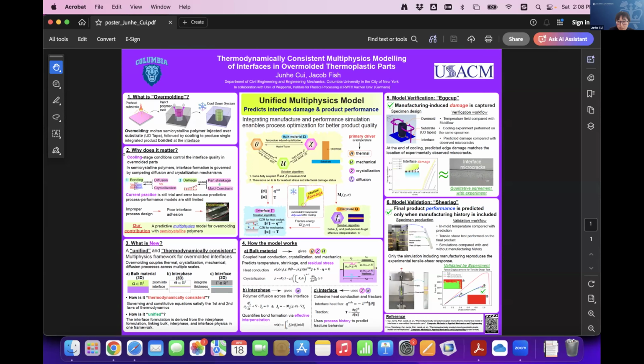Several physical mechanisms happen at the same time. Polymer diffusion across the interface helps the bonding. However, polymer crystallization reduces chain mobility and makes it harder to bond. At the same time, the part shrinkage, together with mold constraint, will generate significant residual stress, damage, or even delamination.